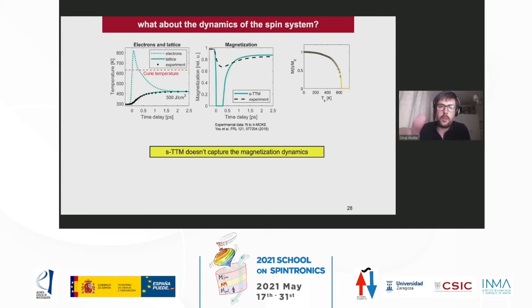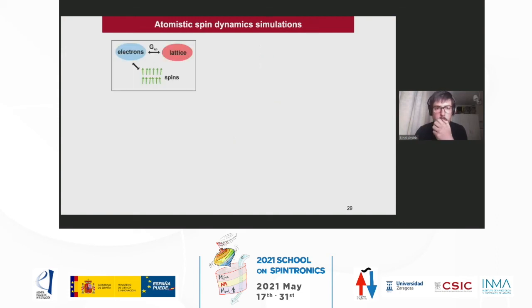So we need to describe the spin dynamics properly. One way to describe spin dynamics within this context of ultrafast magnetism is to use an atomic spin model. Instead of considering spin temperature, we consider a lattice of spins where the energy is given by the Heisenberg model, and the dynamics is described by the Landau-Lifshitz-Gilbert equation.